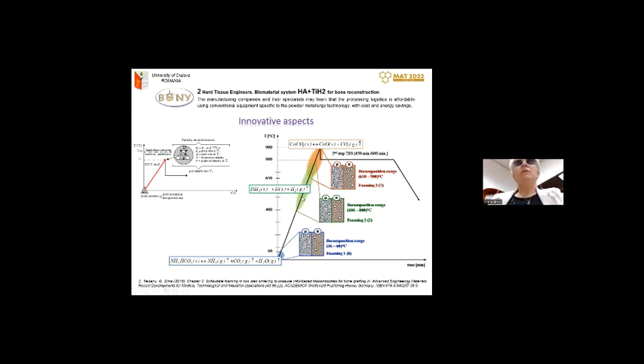This process develops between 400 and 800 Celsius degrees. But before this temperature range, we have the ammonium carbonate, which foams at around 60 Celsius degrees. And the last part of the first step is dedicated to the decomposition of the calcium carbonate, which goes to calcium oxide and CO2. So we monitored these processes in the samples with micronic hydroxyapatite and nanometric hydroxyapatite, and we had a nice book chapter about this, all these processes developing in the first step of the two-step sintering process.